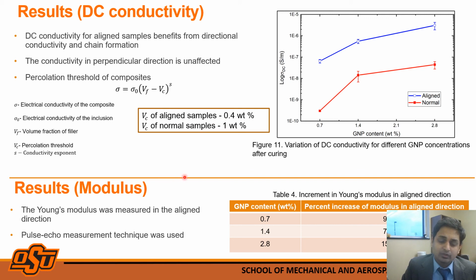Not only does alignment increase the electrical properties, but it also increases the strength in the aligned direction. Table 4 talks about the increase in Young's modulus in the aligned direction. We saw a 9 to 15% increase in Young's modulus because of chain formation and alignment.